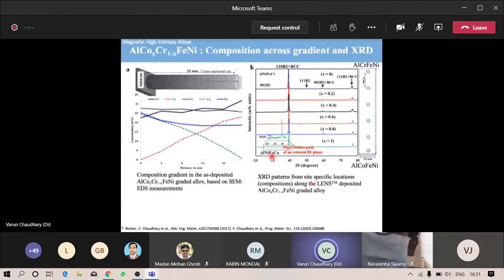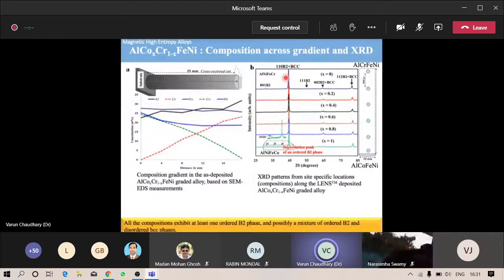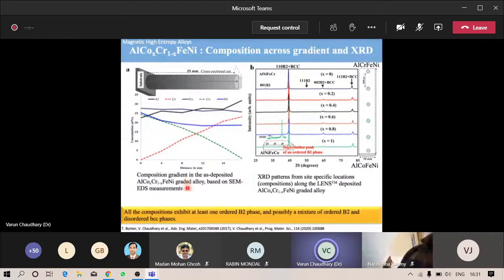Here is the composition across the gradient and X-ray diffraction patterns for these high entropy alloys, and you can see that there is a continuous change in the cobalt and chromium from one side to the other side. Below we have aluminum, cobalt, iron, nickel, and at top we have aluminum, chromium, iron, nickel. All these samples in XRD show some B2 ordering along with the BCC. So we assume that there is at least one ordered phase in these samples, and possibly some mixed phase of ordered and disordered.